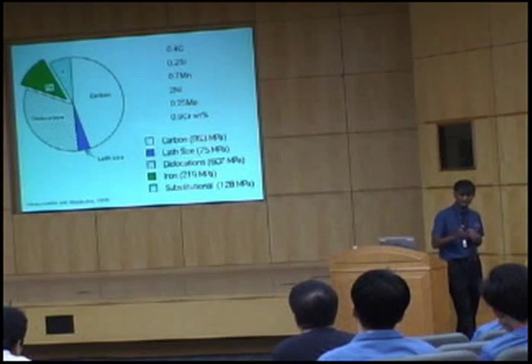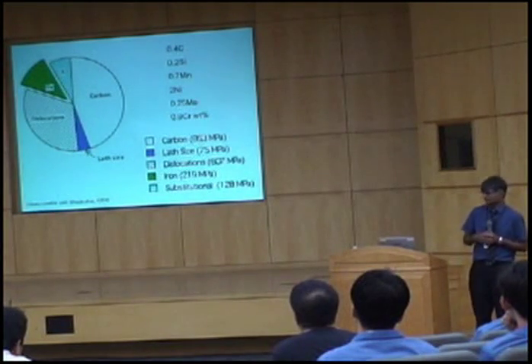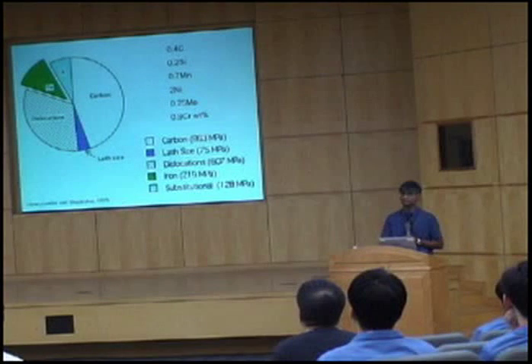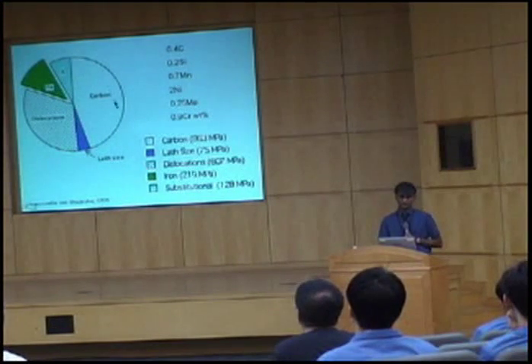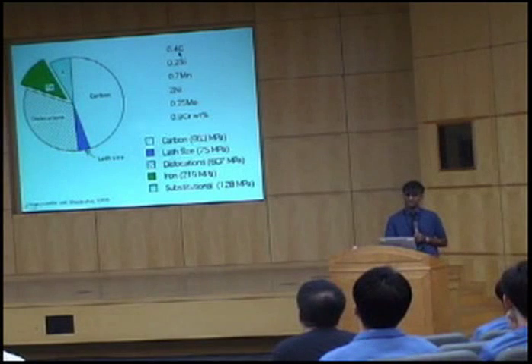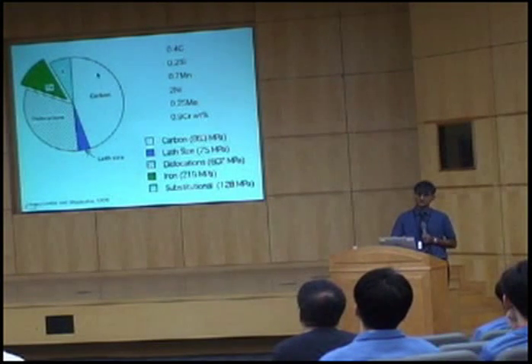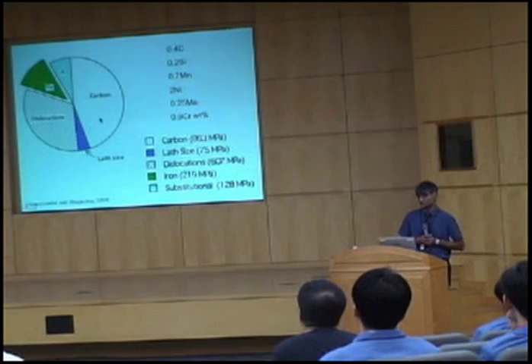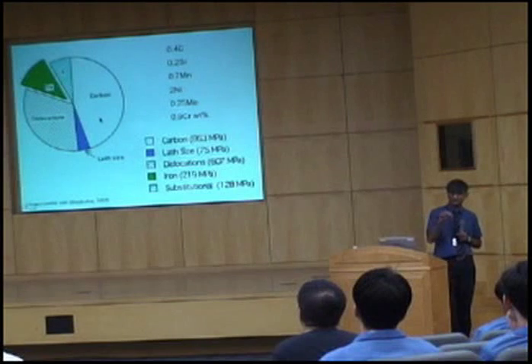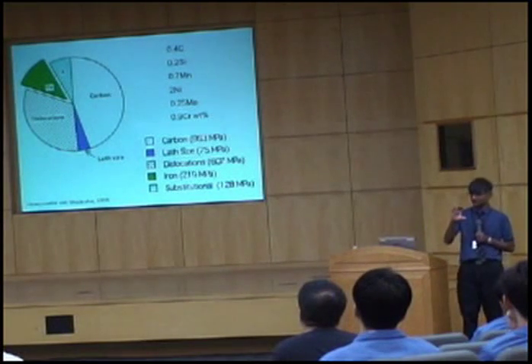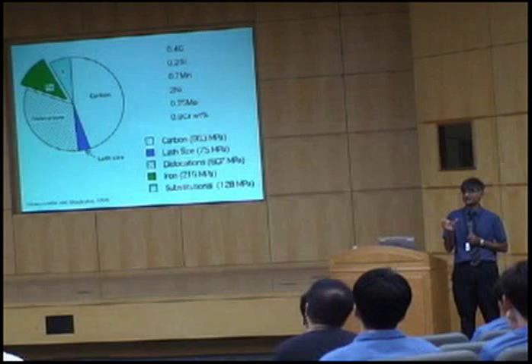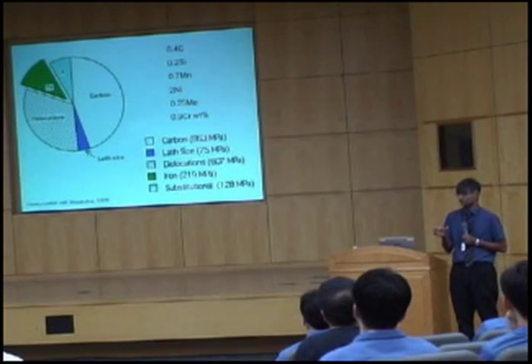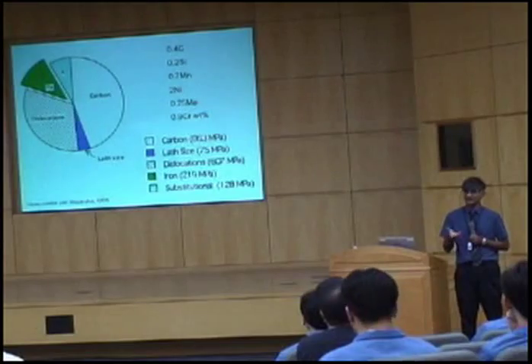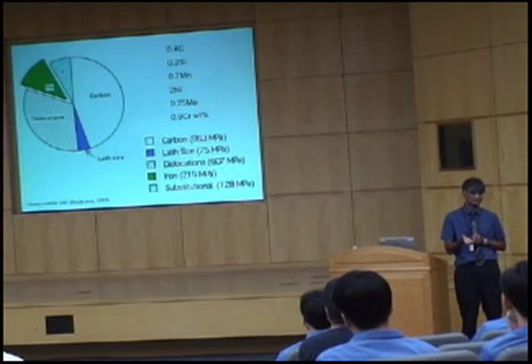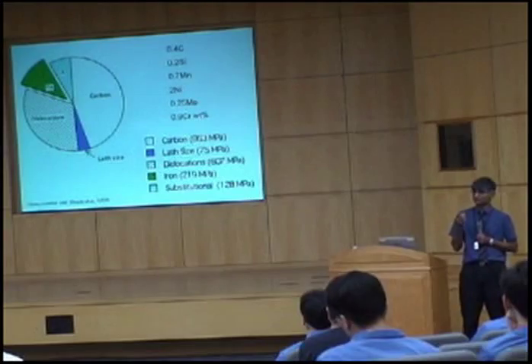Here, what I've done is I've calculated all those components for a martensitic steel, which is simply quenched, not tempered. When you do that, so this is about 0.4 weight percent carbon, most of the strength of a martensitic steel comes from carbon in solid solution, because the carbon sits in octahedral sites which are not regular octahedra. They cause a tetragonal strain, and a tetragonal strain is very powerful in interacting with both the shear and the dilatational components of a dislocation. So carbon in ferrite causes huge hardening.